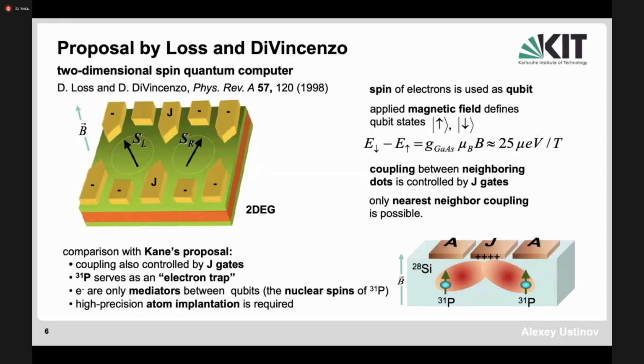And the proposal of using quantum dots for a quantum computer came up a really long time ago from Daniel Loss and David DiVincenzo, where they were proposing to use spin states in quantum dots to carry quantum information. The problem is that quantum dots, of course, carry charge, but as I said already in relation to defects, the charge is not a good degree of freedom because there are many sources of decoherence for the charge states. So there are defects on the surface, there are charge traps, there is charge noise, and all the charges get decoherent very, very quickly.